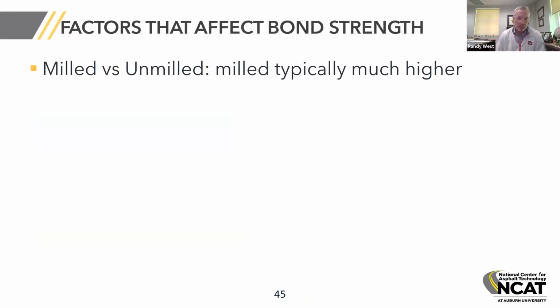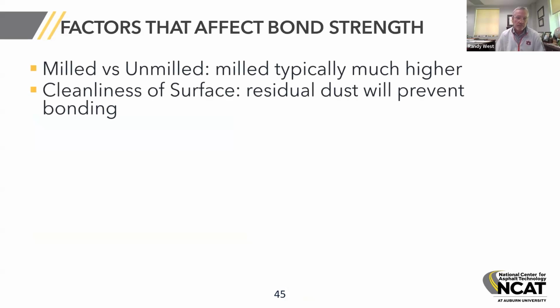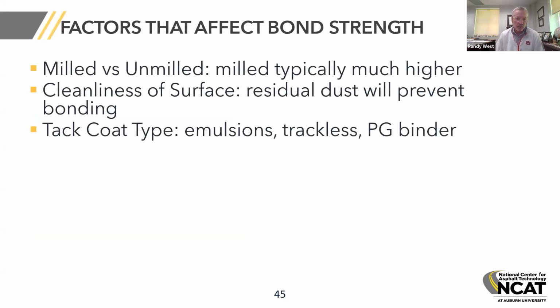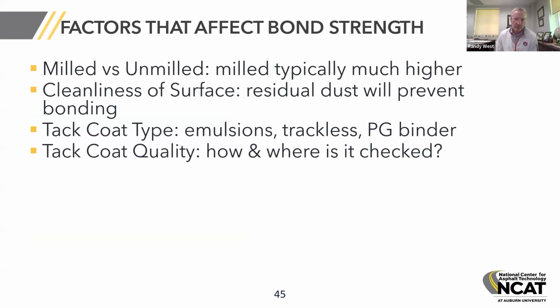So I'm going to wrap it up with factors that affect bond strength. We've already talked about milled versus unmilled. Milled is typically a much higher bond strength than unmilled, but there are exceptions to that. Cleanliness of the surface is important. Residual dust will always minimize or reduce the bond. Tack coat types do matter. Emulsions, trackless tack, and PG binders can all provide good bond if they're applied well and the surfaces are clean.